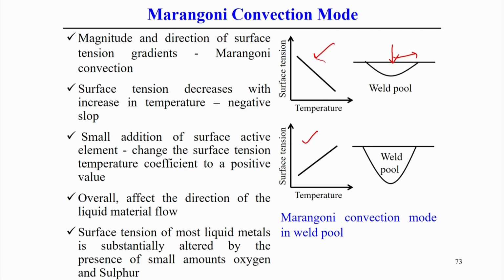In other words, the second case is probably more advantageous if we try to achieve a high depth of penetration, as compared to a wider width. In the second case, the aspect ratio also increases with respect to the first case, and the penetration also increases. So, the second case is more desirable, and that comes from simply adding some amount of surface active elements.